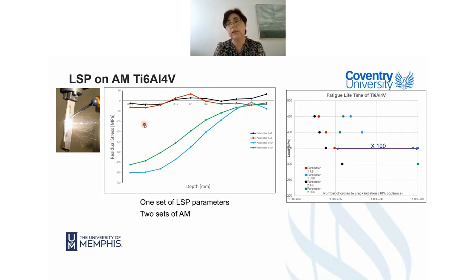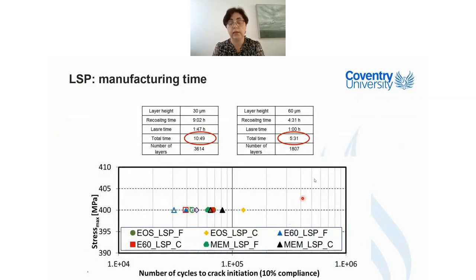And if you look at the grain size, you see that we significantly changed the grain size, making them much smaller. And after that, we did a fatigue measurement. AB is as-built, the original parts, while the other two correspond to laser shock peened samples. The difference is that in one case we used vinyl tape, in another one aluminum. But in all cases, you can see that we were able to increase fatigue lifetime, or the time when we start detecting the cracks.